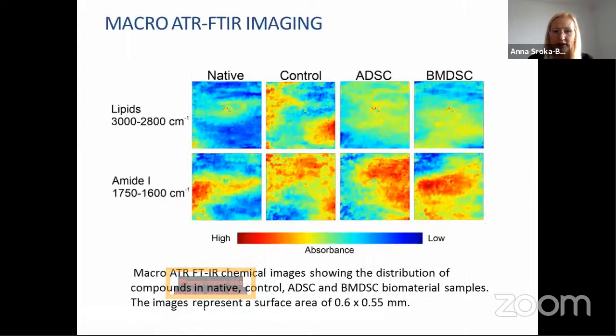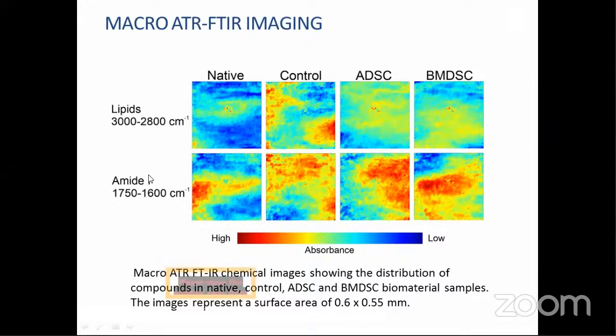And the next part that we used for the analysis were images. So we put the biomaterial on the crystal, then we imaged the surface, and this surface was imaged over 0.6 times 0.55 millimeters. So this is the area of the image. We use the color scale to express high concentration and low concentration, which is the intensity of the bands in the map. And we can notice that there is a different distribution of lipids in the native, control and biomaterial samples. We can also observe a different distribution of the amide bands. So that was one example.